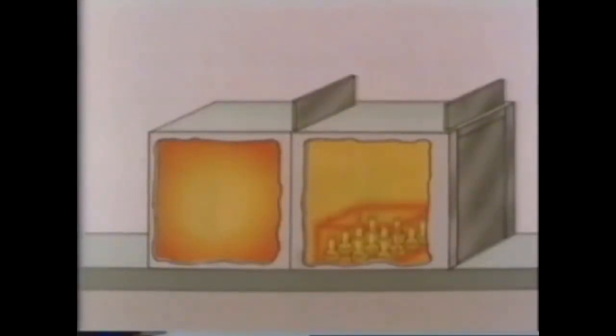An X-ray photograph indicates the type of effect achieved. The carbon case shows up as white. The major disadvantage is that the component now has a coarse, crystalline grain structure. This has been caused by the length of time spent in the furnace at this high temperature. So, after cooling slowly in the outer vestibule, the next stage is to refine the grain of the bulk of the material, the core. This, remember, contains 0.1% carbon, as the original did.